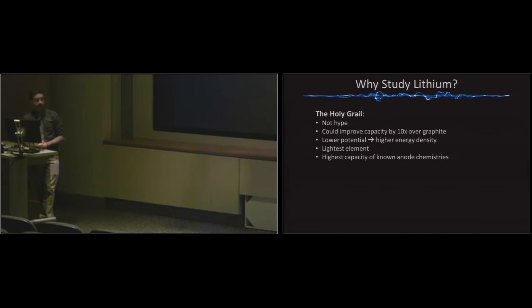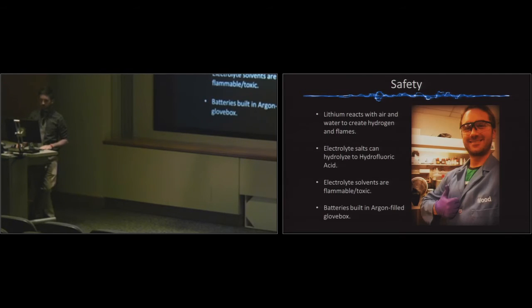You could actually improve the capacity by about a factor of 10 over graphite. It's got the lowest potential, as I said, which would give you the highest energy density. It's the lightest of the elements that's used for energy storage, and so it would give you the lightest batteries. And it's the highest capacity of the known anode chemistries. And so this material really actually is pretty fantastic if we can get it to work. People have been trying for about 40 years and had no success.